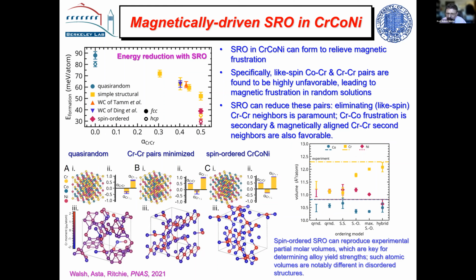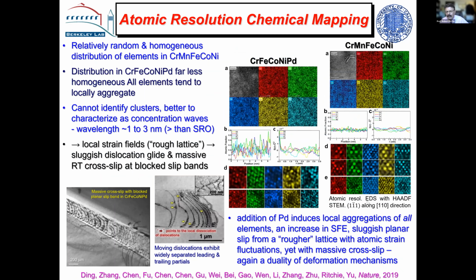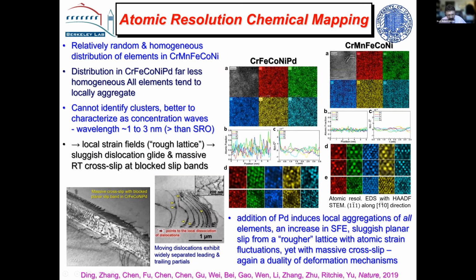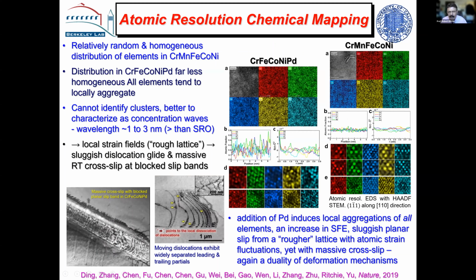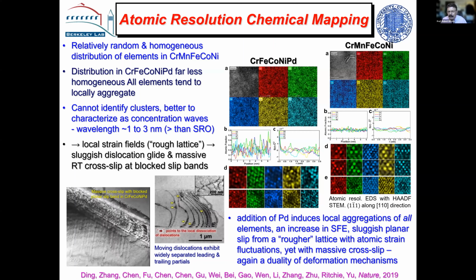But let's see if we can see it. And this is what we did a lot of work on. The first work was done by a researcher at Zhejiang University, and she used atomic resolution EDS in the STEM, and looked at basically the Cantor alloy, but replaced the element manganese by palladium. The reason to do this was to get a different atom, which would have a different atomic radius and a different degree of electronegativity, to try and see if there's any change in order. And they do scans, and they're looking at columns of atoms, and they can get basically the concentration of those columns. It should be random.